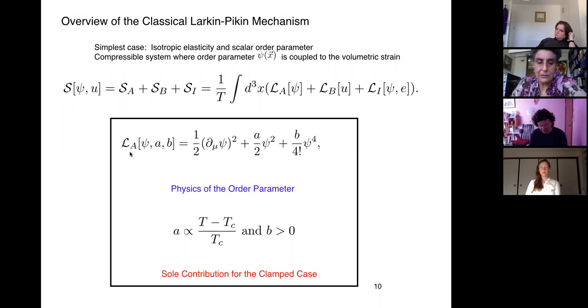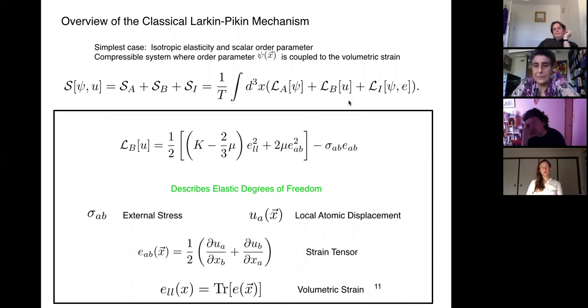Okay, so let's define these terms. The Lagrangian term A is just the physics of the order parameter. In the simplest case, it's a phi-4 theory. A is the tuning parameter proportional to temperature, and B is the quartic coefficient. Because we have a second order transition, B is greater than 0, and A is of course proportional to the reduced temperature. In the clamped system, this is the sole contribution, so then we have a very nice second order transition. So this is the physics of the order parameter. Now, what's L_B? L_B is a function of the local atomic displacement, and it describes the elastic degrees of freedom. Here, sigma is the external stress, u_a is the local atomic displacement, e_ab is the strain tensor, and e_ll is the volumetric strain. So this term describes the elastic degrees of freedom.